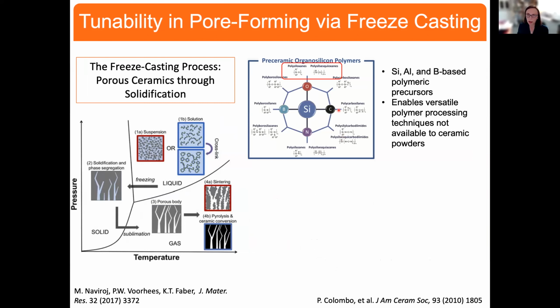Paolo Colombo has done some extensive work on pre-ceramic polymers, and he and a couple of colleagues wrote a very beautiful paper that describes a great deal of work on these pre-ceramic polymers. This figure up here in the middle is a demonstration of the various pre-ceramic polymers that range from polysiloxanes to polycarbosilanes that allow you to make a lot of silicon-based ceramics. And that ranges from ceramics that include silicon, aluminum, and boron, just by virtue of the pre-ceramic polymer that one uses. We focus our work on the polysiloxane, and the reason is that when the pre-ceramic polymer converts to a ceramic, there's a pretty high yield, and that's to our benefit, okay?